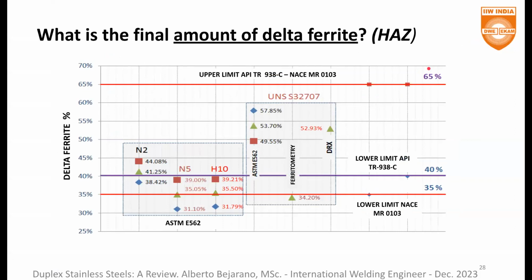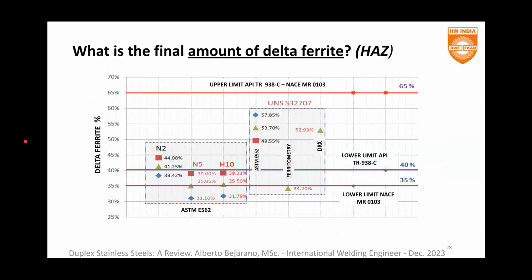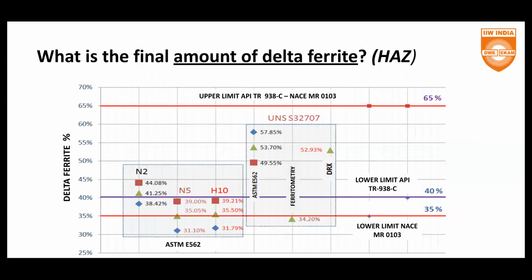So if my amount of delta ferrite is between these two limits, we have done a good job. And again, the best option is to measure the delta ferrite during the qualification process, not during the welding in the field, but in the qualification of the procedure. Okay, use ASTM E562. Okay, very good.